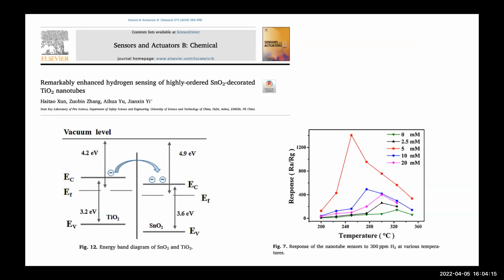So now in the next graph you can see the response of the sensor first increased and then decreased with increasing precursor concentration, following the order of 0, 2.5, 5, 10 and 20 mM. So you can see for 5 mM it is maximum, in the red line.